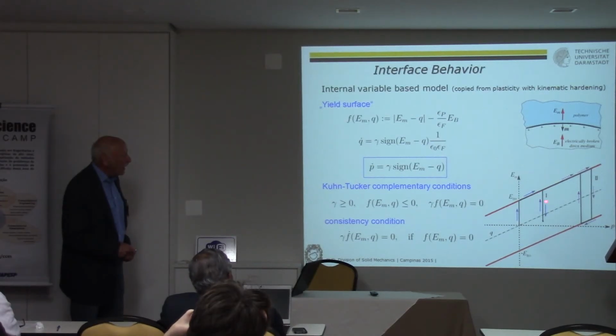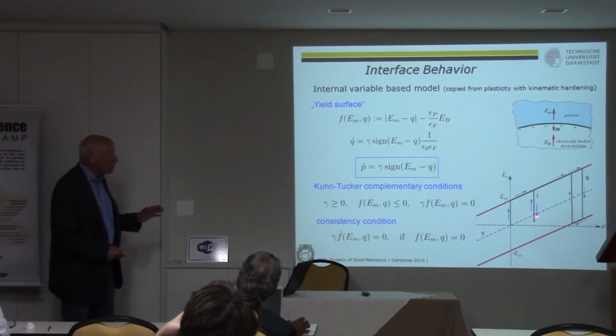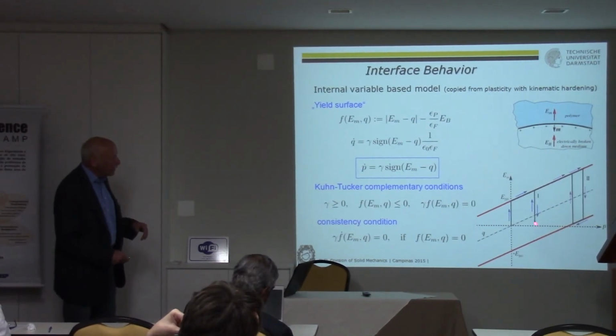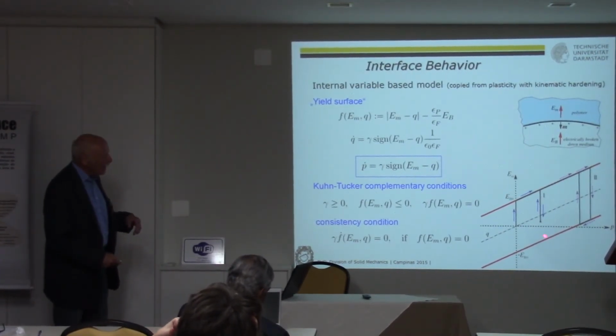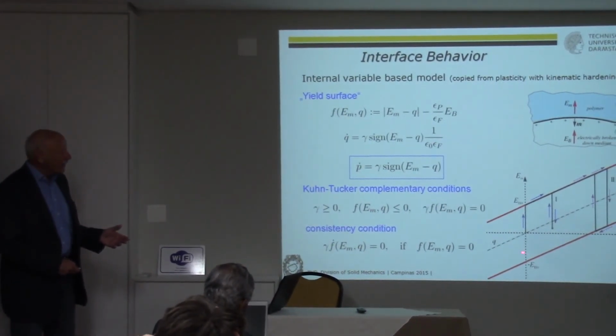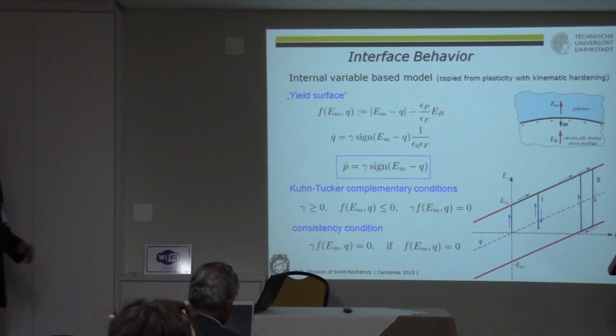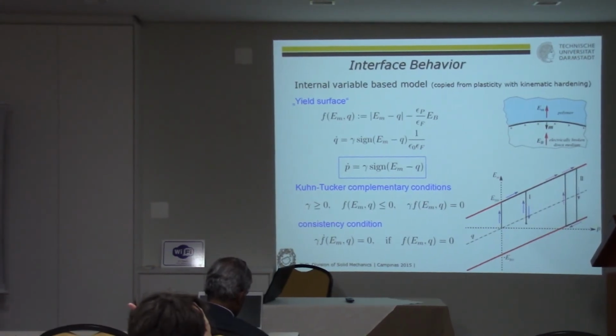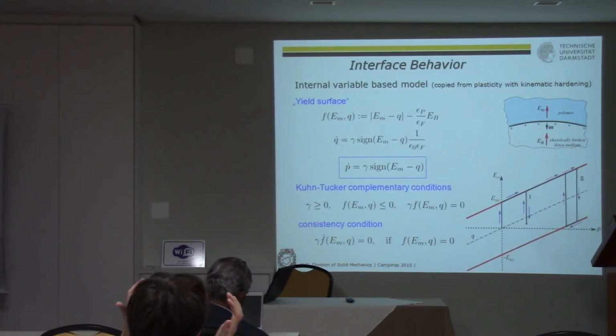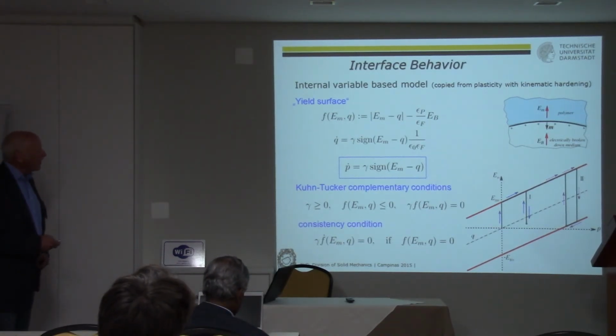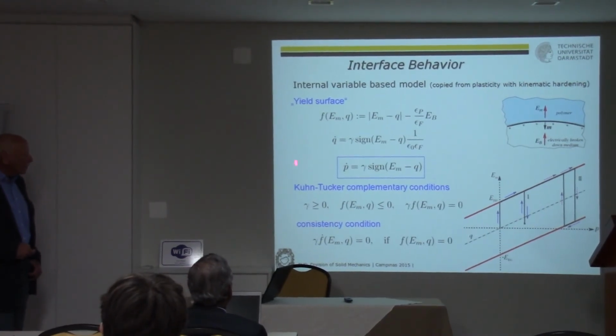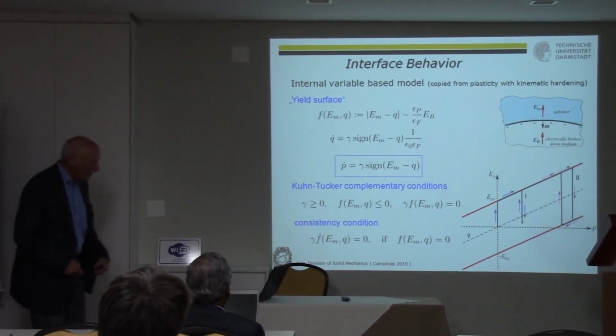And then if you unload the material, yeah, then there is no longer breakdown, but the P remains constant, yeah. If you go to the other direction with your loading, you here touch this red curve, yeah, and breakdown takes again place, yeah. And if you look at this system, this looks exactly like a one-dimensional material where you have kinematic plasticity, yeah. And we can use all the tools from plasticity with kinematic hardening, yeah, to describe such a material, yeah.